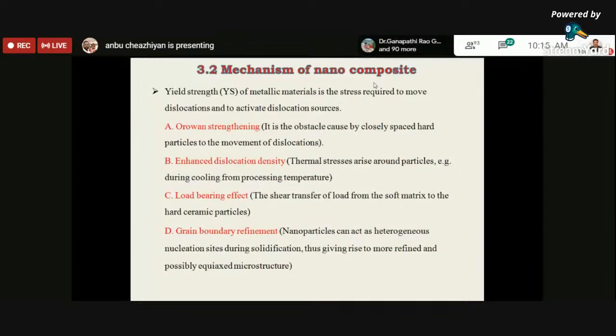Next I'm going to discuss the strengthening mechanisms of nanocomposites. The yield strength of a metallic material is the stress required to move the dislocations and to activate the dislocation sources. Generally metal matrix composites are strengthened by enhanced dislocation density, load bearing effects, and grain boundary refinement, which are called strengthening mechanisms. In the Orowan mechanism, it is the obstacle caused by closely spaced hard particles to the movement of dislocation.